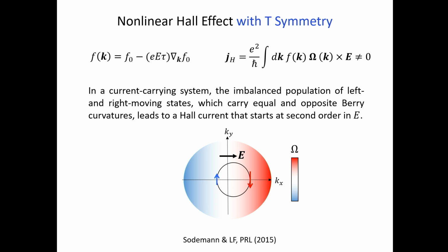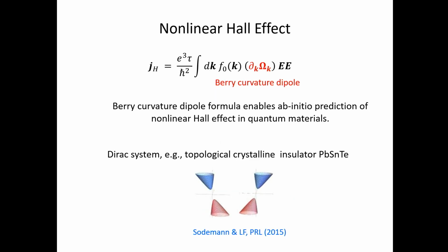And then this Berry curvature further drives an anomalous current, which is now second order in the electric field. Because of this, in time-reversal symmetric systems, we can get a Hall current that starts at the second order due to this equal and opposite Berry curvature at opposite momentum. And in fact, one can find a very compact formula for this anomalous Hall current at the quadratic order. It requires thinking about the distribution of Berry curvature in momentum space, basically the derivative of the Berry curvature with respect to k, integrated over all occupied states.